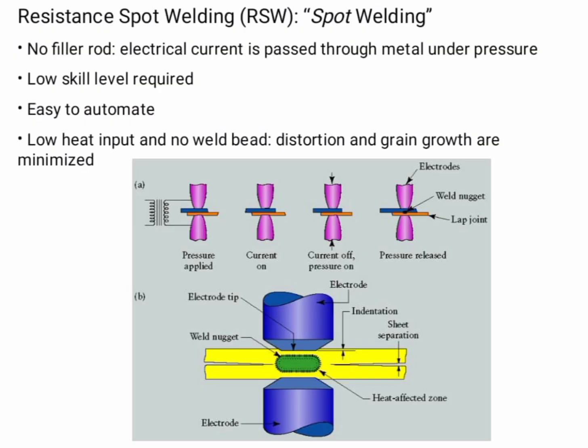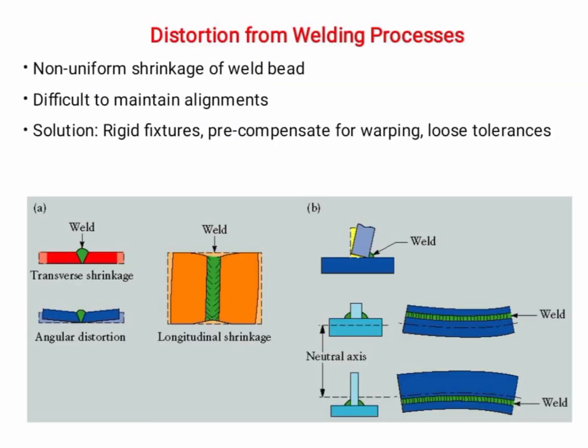We also have resistance spot welding, in which no filler rod is required. Electrical current is passed through the metal to heat it under pressure. Low skill level required, easy to automate, low heat input, and no weld beads. Distortion and grain growth are also minimized. Distortions from welding processes are non-uniform shrinkage of the weld bead and difficulty maintaining alignment, and the solution for this is rigid fixtures, precompensating for warpage, and loose tolerance.